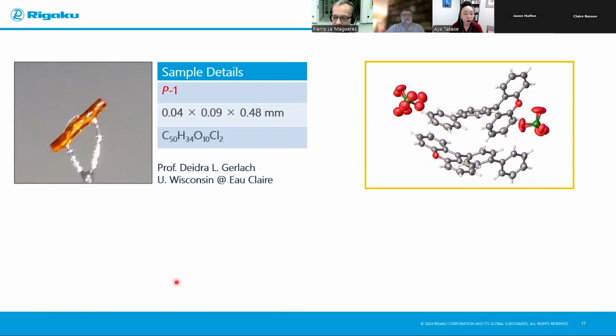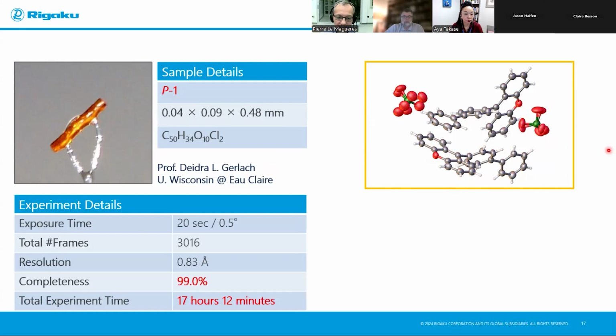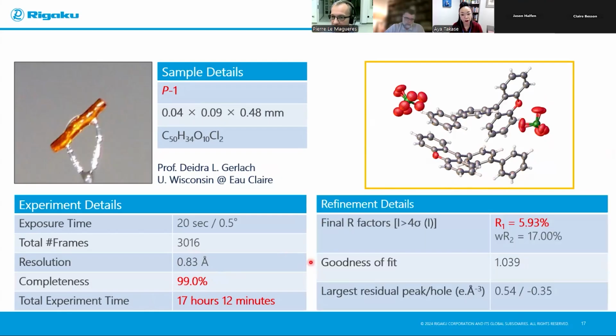Second example, with another low symmetry crystal, P bar 1. So now at least we've got a center of symmetry within the crystal, but again, a very thin crystal, 40 microns. This is a data set that was provided to us by Professor Gerlach from the University of Wisconsin at Eau Claire. As you can see on the right-hand side, that compound was also an organic compound. It's a salt of perchlorate, and adding to the fun, the perchlorate anions were, of course, disordered. The data was collected in 17 hours, so if you think about it, this is just an overnight data collection. Again, 99% completeness to 0.83 angstrom resolution. The disorder of the perchlorate anions could be properly modeled, and the whole thing yielded an R1 just below 6%. So really nothing to be ashamed of at all.